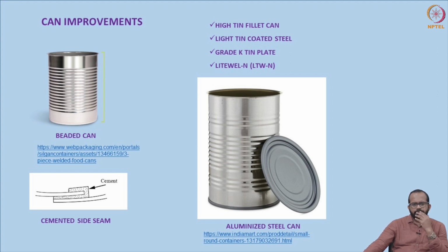There are also high tin fillet cans or HTF cans, which are widely used in the canning of spinach and tomato, basically high acid foods. High acid foods which have additives such as oxalates and nitrates have a de-tinning effect. De-tinning effect means the tin coating is removed because of these components, which affects the product color. So an extra tin fillet is provided, which acts as a sacrificial anode. The de-tinning effect will be from the fillet rather than the can. So it is called a high tin fillet can.